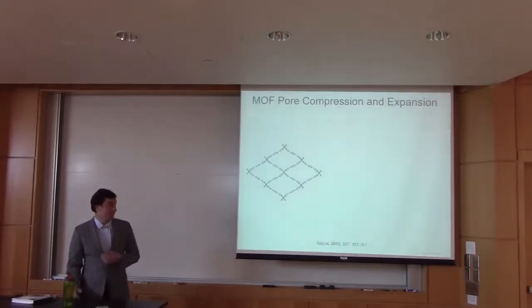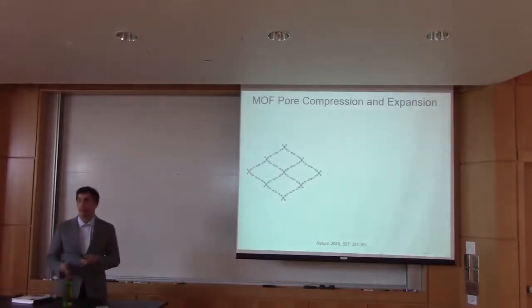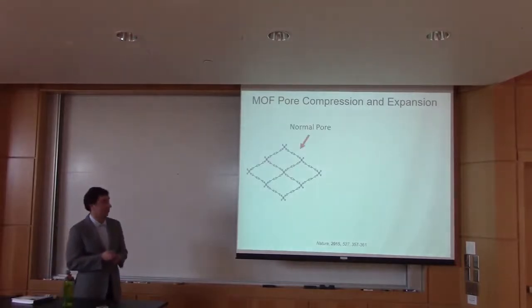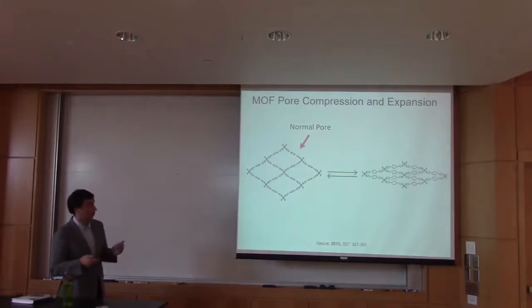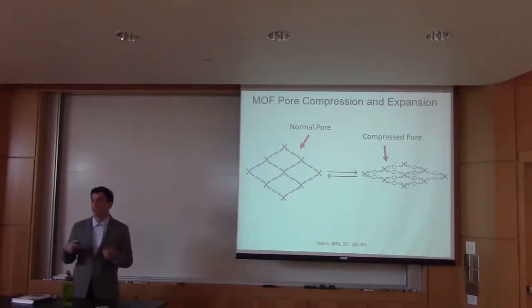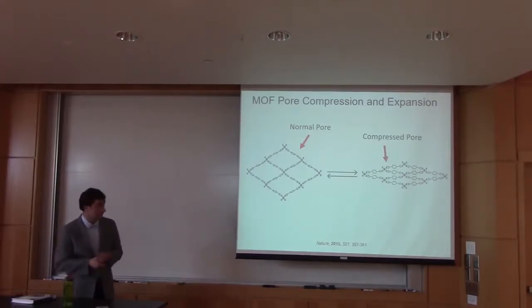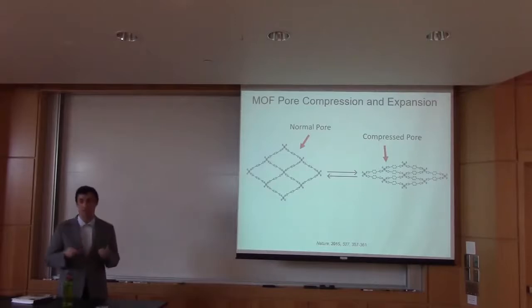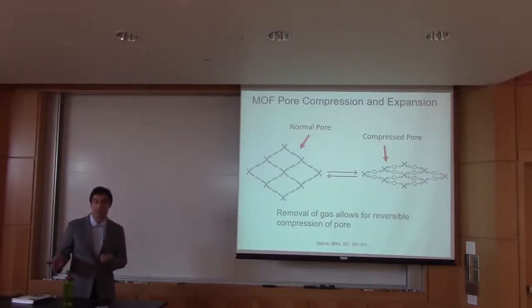So after trying a few things, my mentor suggested that what we're seeing is actually a function of MOFs and a feature. This is work put out by Jeffrey Long's group at UC Berkeley. This is a normal MOF with its representative pores being held open, and as we pull vacuum, we can compress these pores, as there's nothing holding those pores open, no solvent, no gas. And this arrow going both ways shows the process is reversible. So they're able to basically expand and contract their MOF pores by using vacuum and re-added gas or solvent.